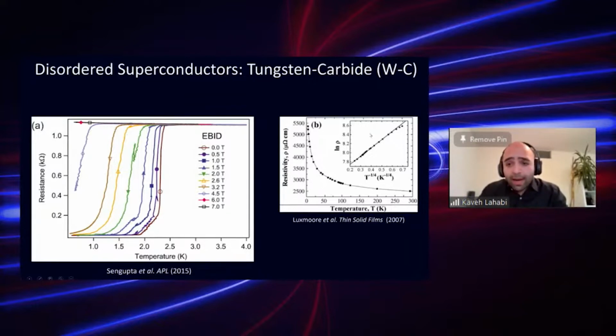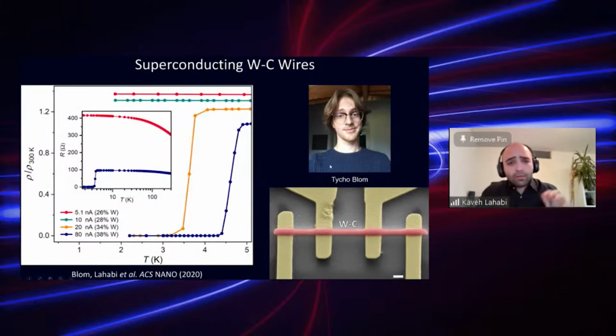And my bachelor student at the time started printing tungsten carbide wires, like the ones you see here. And of course, one day he managed to make a wire which had a transition temperature of 3.5 Kelvin, which was already higher than the previous reports. So when we looked into it, we found out that what Tycho was doing was using much higher beam currents than the previous reports. And I think that was the main breakthrough.